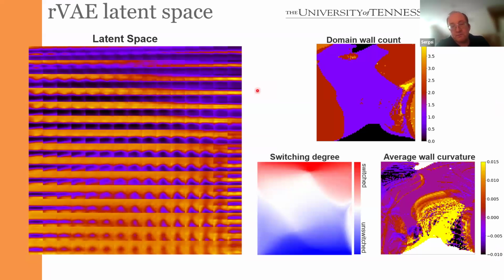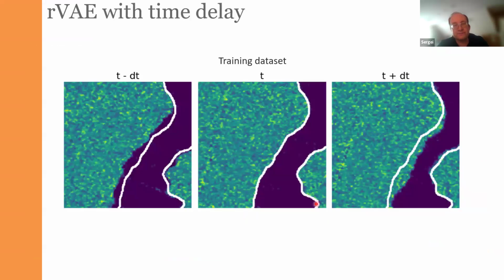And then we can see how the physical parameters change across this latent space. For example, this is our degree of switching, which is simply the ratio of the dark to bright regions. You can see that it is relatively well distributed across the domain space. This is our average wall curvature. So this is the domain count. So again, these are human interpretable quantities. But interestingly enough, these human interpreted quantities have complex but relatively smooth and organized representations across the latent space.